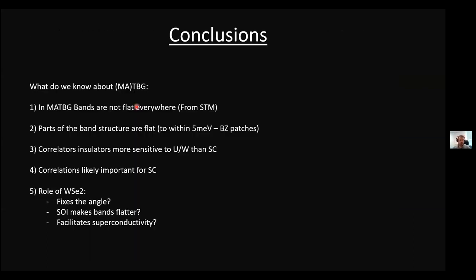And this brings me to the conclusion of this part. So what do we actually know about magic angle twisted bilayer graphene? We know from all these STM experiments that we and several other groups, Columbia, Princeton and Rutgers, did, that even at the magic angle the bands are not perfectly flat. At least they are not flat everywhere. You only have parts of the Brillouin zone that are flat, and you have dispersive bands.